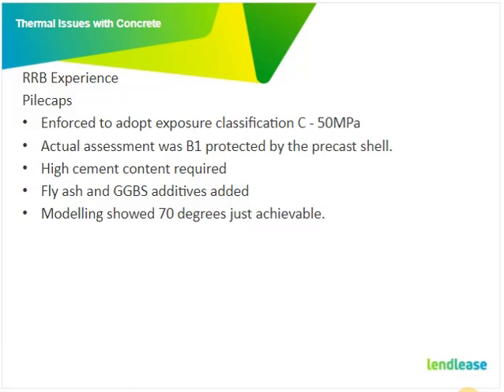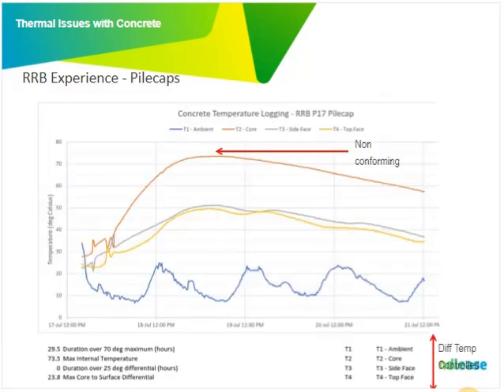High amount of cement content. We had all the additives. The modelling showed 70 degrees was just achievable. So I think in this case we do show that we did exceed the 70-degree limit. So, you know, with all those controls applied and all those sorts of things, you still can't meet it. Non-conforming. But differential temperature was controlled.